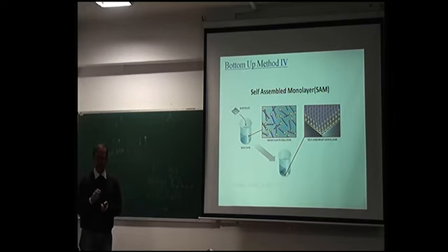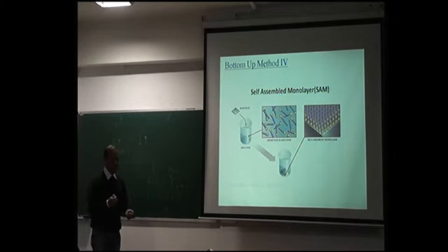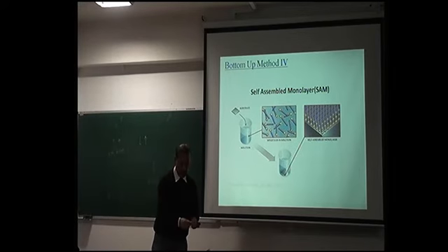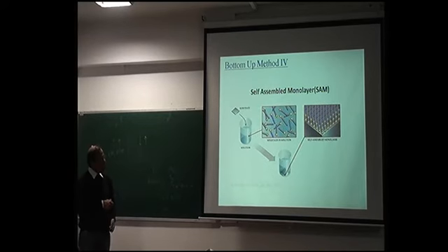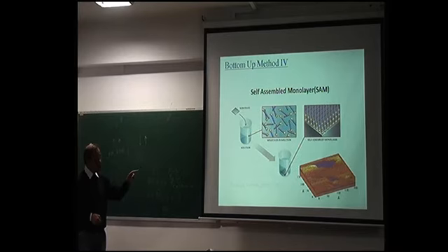It's very simple. You can even do the flame annealing with a candle. That's not a problem. And then you put that substrate in the solution, just keep it for 12 hours, and you will see just one and only one monolayer forms on the gold surface. Okay? And this is the STM picture of that monolayer. You can say it's a beautiful picture. This will cost you probably $1, but the same structure, if you want to make it by MBE, you need almost close to $2 million. Okay?